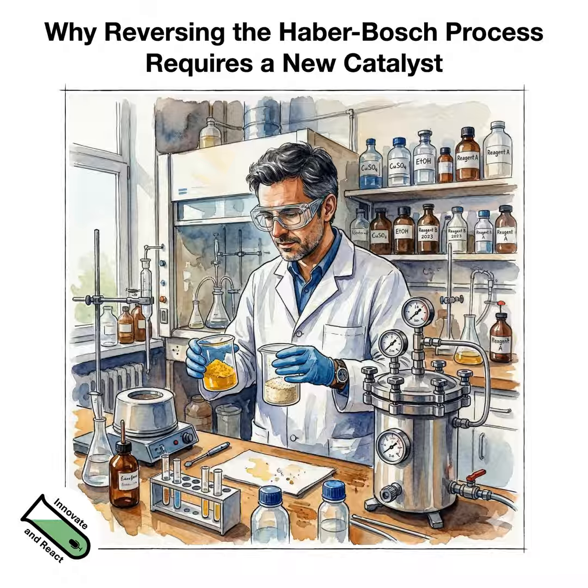And this is more or less a breakdown of that concept of microscopic reversibility, which is in principle only true if you look at forward and backward reactions at exactly the same reaction conditions. But if you do ammonia synthesis at 200 bar, and you look at ammonia decomposition at 1 bar, then that has an effect on the chemical potentials in the reactor, obviously. And those also would affect the catalyst. That's a manifestation of catalysts being dynamic to some extent. They develop their active structure often only in contact with a reactive medium.